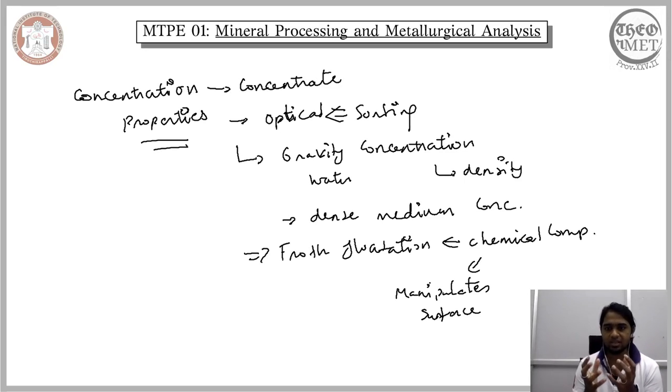What I mean by that is, this chemical reagent that we use interacts with the mineral in such a way that it makes it hydrophobic, meaning it makes it water repellent. So it will not change the chemical composition of the mineral, but it will make the surface of the mineral water repellent. The interaction between the chemical reagent and the different particles will not change the chemical composition of the particles, but rather it manipulates the surface in such a way that these particles are either attracted towards water or repelled by water.